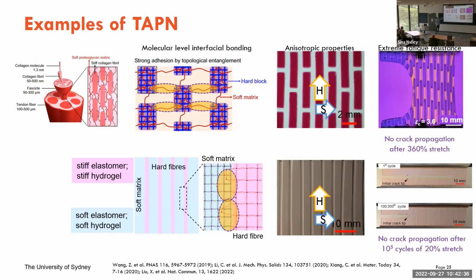So if you look at that one on the right side, there's a notch introduced into this material. And what you see is actually a crack being stretched 360%. It doesn't propagate. All right. And the reason is those glowing yellow areas are polarized light showing the concentration of stress. The way these are put together, and because they are completely integrated, means that the stress has been distributed over the whole length of material.